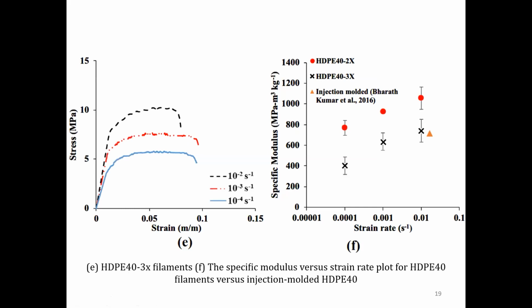One more thing, what we generally do in our research group is we don't directly jump into 3D printing. So we do injection molding of the similar system, and then we compare the tensile test. We do a tensile test on a dog bone sample made in an injection molding machine. That result is here, okay? And then we compare this ASTM standard dog bone sample tensile test at the same strain rate for the filaments before jumping into 3D printing.